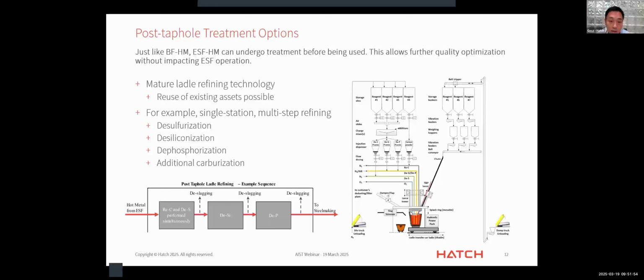One example is the system that we provide, and we like to integrate it as part of our overall furnace solution: single-stage and multi-stage refining, where inside a hot metal ladle you can adjust sulfur, silicon, phosphorus, and achieve additional carburization if needed, in a single stage or in multiple stages. Again, these are very mature technologies.